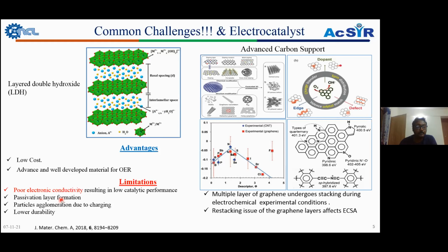And the third thing is particle agglomeration, because the layered double hydroxide has a particular size, so without any support systems each individual particle has a certain charge, so there is an interaction and that can form particle agglomeration due to the charging. The second thing is that only a layered double hydroxide, only an oxide or hydroxide system, cannot sustain for a long time. So based on the current advanced research on carbon supports, we could see that any kind of carbon support can be used.